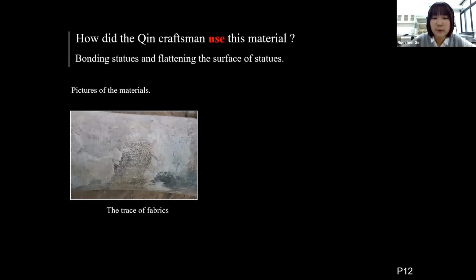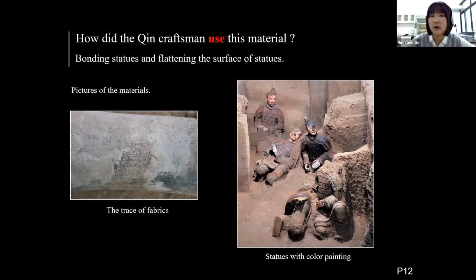Such cases were also found along with obvious traces of fabrics, which was probably another way of flattening. In the beginning, the statue surface with strands was wrapped by fabrics for a preliminary filling, and then the studied material was used to flatten the surface because the rich fibrous structures allow the material and the statue to cling tightly. As you may know, there is a layer of color painting on the surface of statues, so flattening can make the surface smooth enough to show the color.